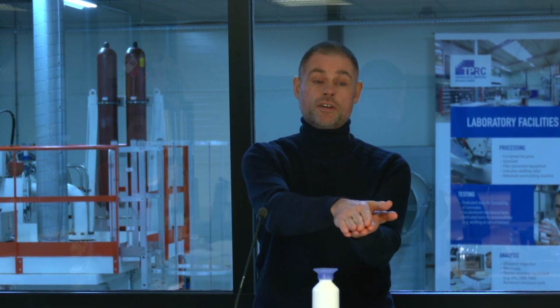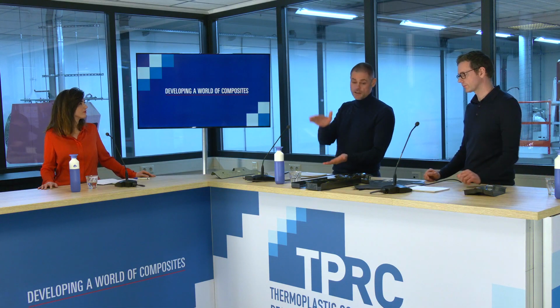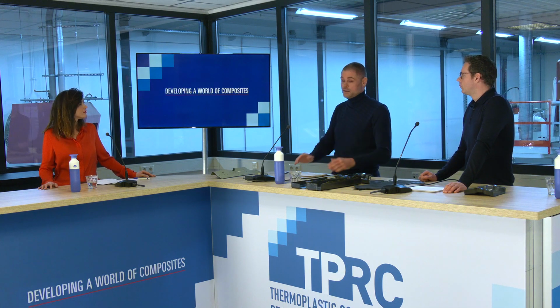So deconsolidation in the oven is the problem. But even if you manage to melt the material and transfer it to the press without it falling apart, you only have this very short time of maybe tenths of seconds to consolidate the material, to drive out all the air that is inside. And this time is simply not there.